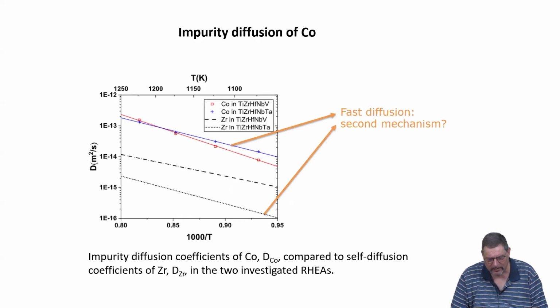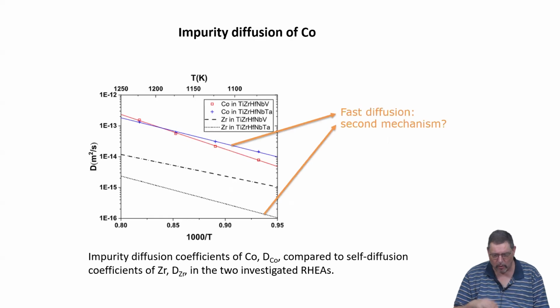When we now look at an impurity tracer diffusion, cobalt is not part of the alloy. So when we measure tracer diffusion of cobalt in these alloys, it is an impurity diffusion, right? So we have to take into account that there is a different contribution from the diffusion entropy relating the mixing of a new element with the given constituents of the base alloy.